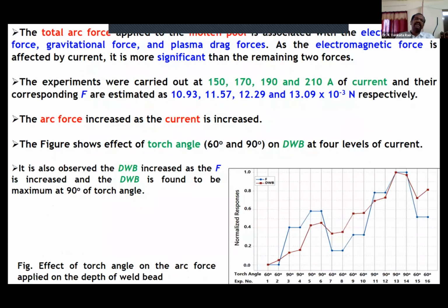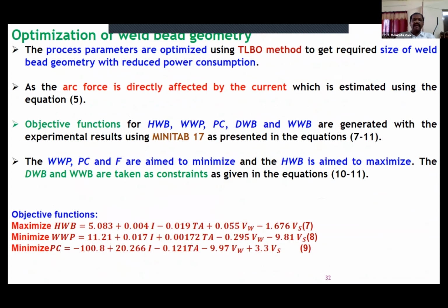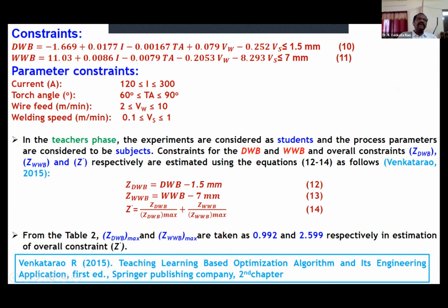Simply take the experimental data and put it in Minitab, where you have regression analysis. Using that regression analysis, we can generate these equations. If the R square value is above 0.9, then only should you take the linear equations. Our aim is to maximize the height of weld bead, and minimize the width of weld pool and the power consumption. The depth of weld bead and width of weld bead we cannot minimize, but they are restricted.